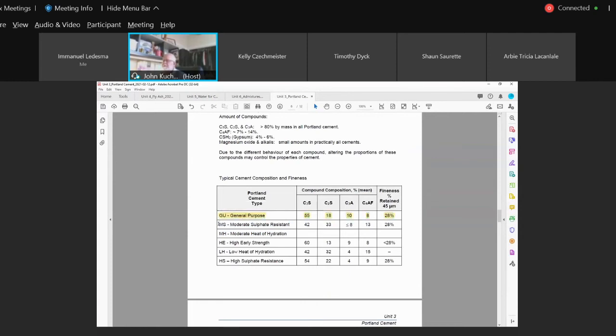MS, moderate sulfate. MH, moderate heat of hydration. HE, high early strength. LH, low heat of hydration. HS, high sulfate. In Winnipeg, we use HS for anything below grade: caissons, piles, maybe grade beams that are buried, maybe walls that are buried for an underground parkade. Anything exposed to our clay soils in the Winnipeg area, HS, automatic, no ands, buts, or ifs about it. GU, general purpose, is basically our Portland cements, anything above grade, pavement, slabs, anything above exposure to sulfates.